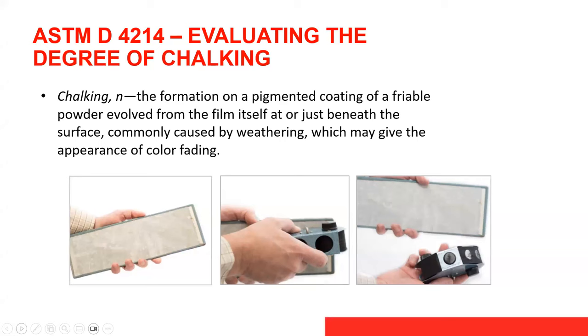And the chalking itself is actually the film breaking down. That breaking down of the film really is the resin that's starting to be damaged by the sun and the weather. It's releasing a lot of the pigments and filler particles that are used to formulate the coating. And you tend to get a white chalky surface over time, which is more apparent, obviously, with a deep tone or a bright color than it would be with, say, a white coating.